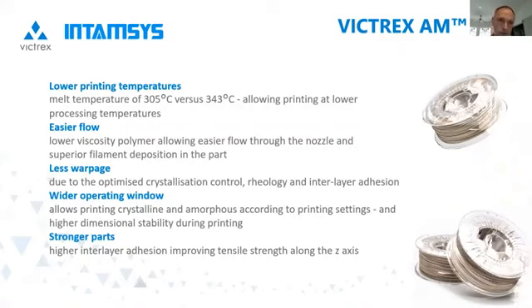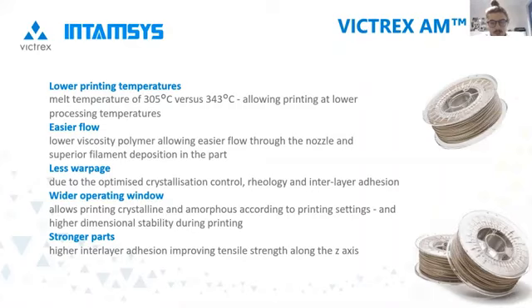And you also saw the flexibility for you to choose which method works best for your application and equipment. So again, you can print amorphous and leave it amorphous, you can print amorphous and anneal it, or directly print crystalline. So one grade that allows you that flexibility. And you also saw the interlayer adhesion and how that boosts the ZX strength and allows the properties to be near isotropic prints. So I hope you've seen that there are growing and increasing options becoming available to you to enable you to print quality parts from high performance polyketones.